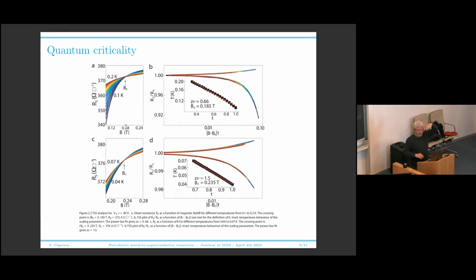Now, if you plot the curves with fields larger than Bx or smaller than Bx with some scaling variable, which is a reduced temperature, you have two scaling behaviors, one above the critical point and one below the critical point. And you have this dynamical exponent, which is almost 2/3. Now, if you go to lower temperature, you have another such crossing point where, again, your resistance is almost constant as a function of temperature. And again, you have good scaling with yet another exponent, which is 1.5, that is 3/2. So you have a crossover between two quantum critical regimes in your system. These are just magnified views.